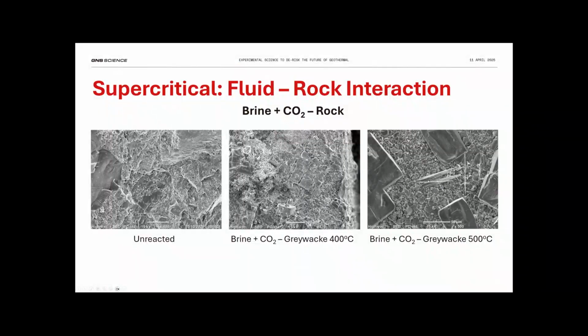So what we think is happening is the pH is so low with the CO2 added that it's aggressively attacking the rock and it's releasing a lot of calcium, and that's forming the anhydrite. But it's also releasing a lot of aluminium and silica from the rock surface, and it's being reprecipitated so rapidly that quartz never saturates. And so quartz cannot grow. And it's because of the lower pH, we suspect, at 500 degrees.